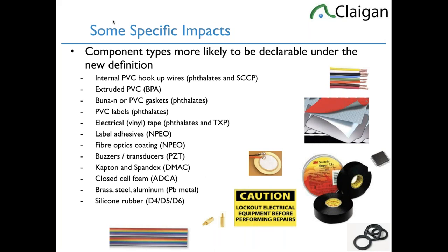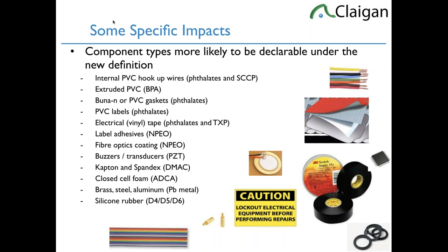Now the declarables, the component level, brings in tons. One of the most common is PVC components and hookup wires. You have phthalates and SCCPs. Now, short chain chlorinated paraffins, or SCCPs, are REACH SVHCs, but you can't declare them. Everything else we're going to talk about here doesn't apply to them. They're banned in Europe and they're banned in Canada at 0.15%. Above that level, it's a recall issue. About a third of those recalls we talked about in the EU were this chemical.